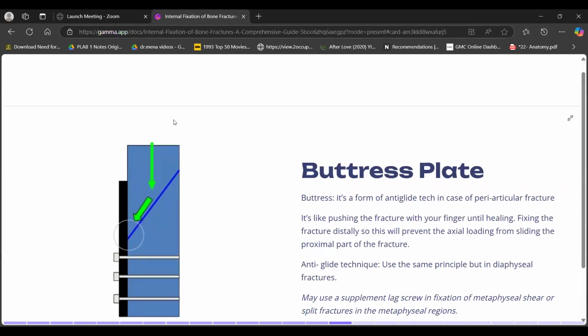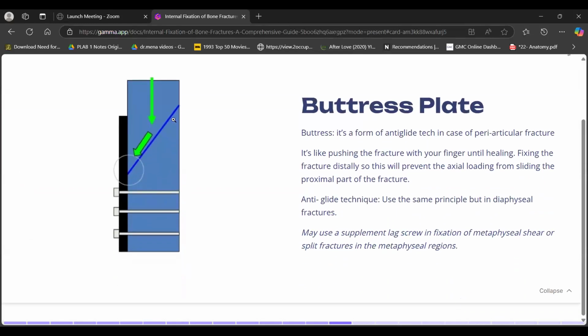The buttress plate, as we can see here, is a form of anti-glide technique for peri-articular fractures. So we use this plate just to push the proximal part of the fracture, just to keep it still. It's like someone putting his finger on the fracture just to push it until it heals. So we use the plate to achieve this target. And we can also use a supplemental lag screw to avoid metaphyseal shear in the metaphyseal regions.